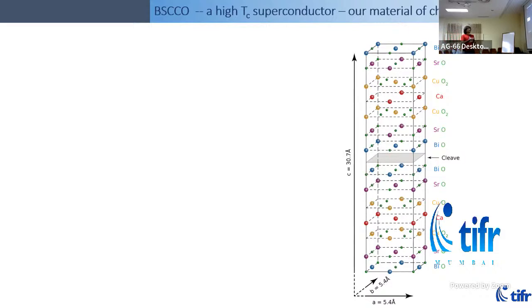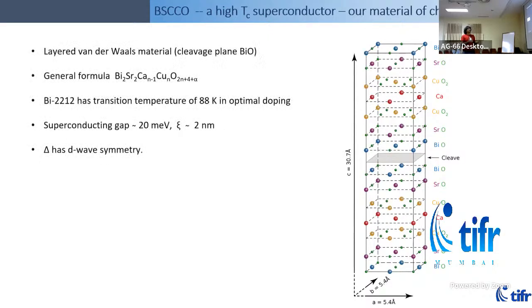So it has a complex structure, and I won't talk about it, but the unit cell is about 3 nanometers tall, and people have demonstrated that down to 1 unit cell or half a unit cell, which is basically one side of the copper oxide planes, you get the superconductivity as that of bulk. So the superconductivity in 1 unit cell thick BISCO is the same as that in a bulk crystal. So it's a D-wave superconductor, which is also well known.